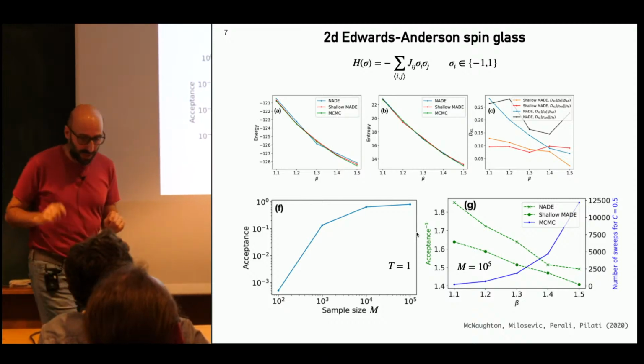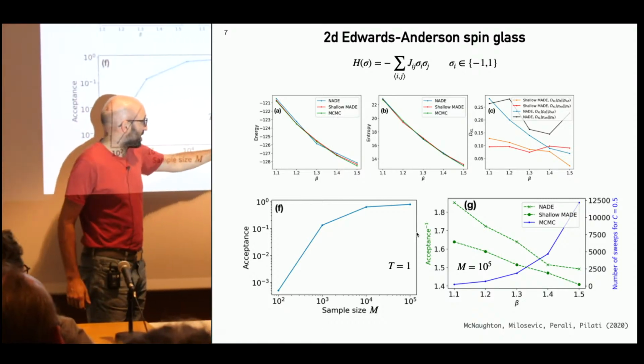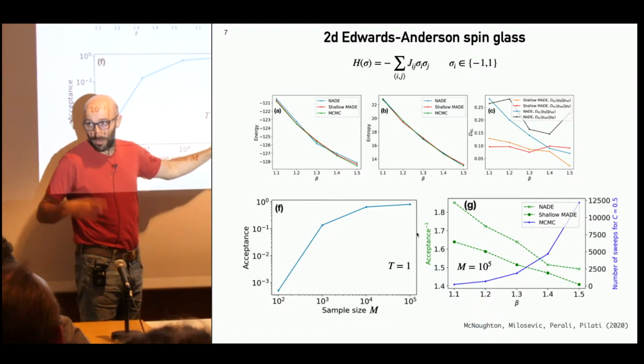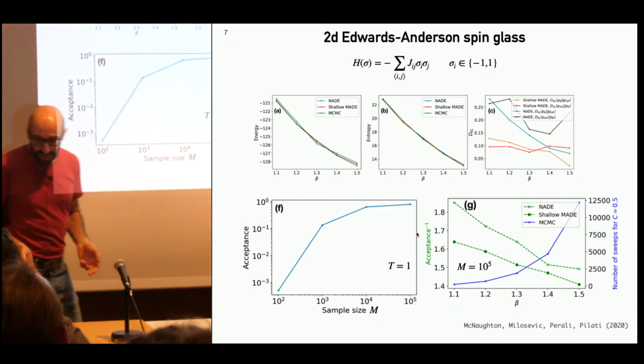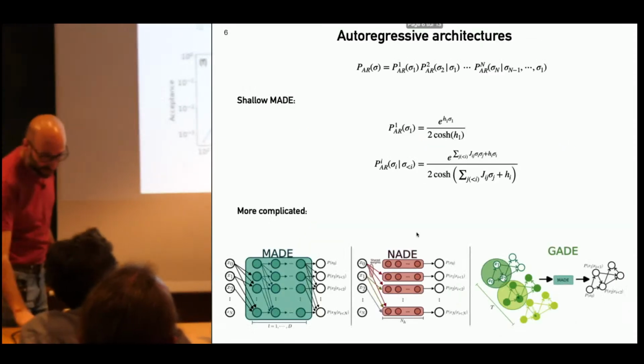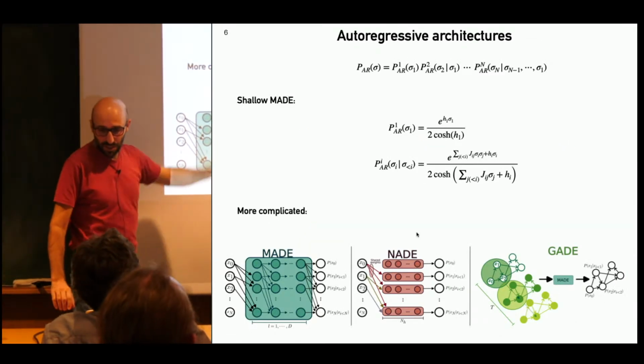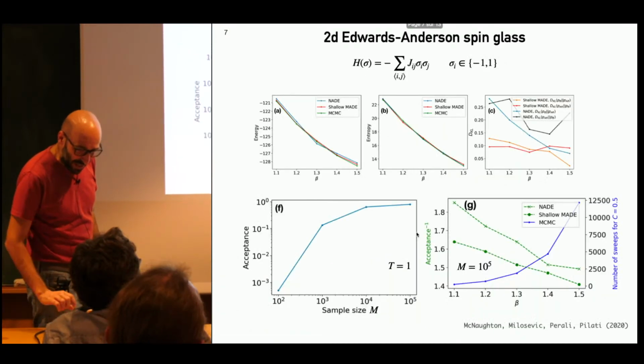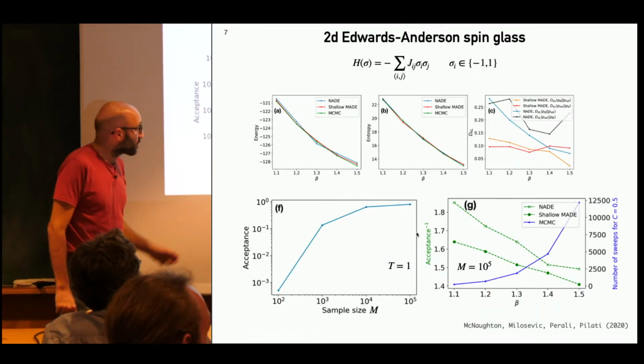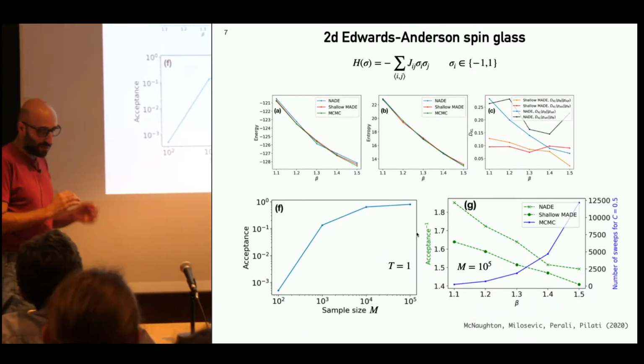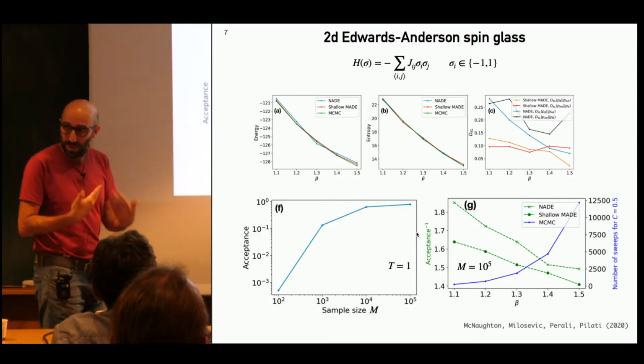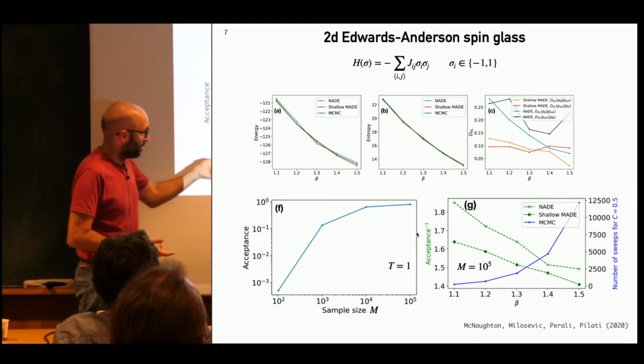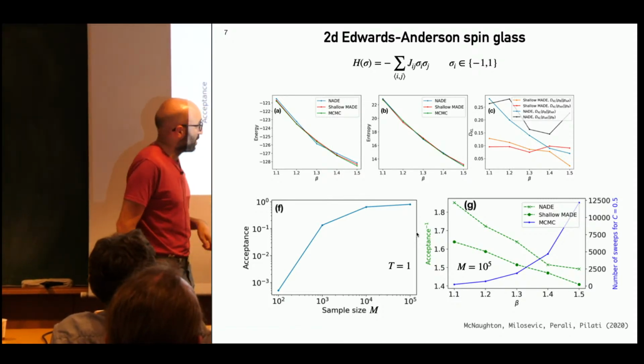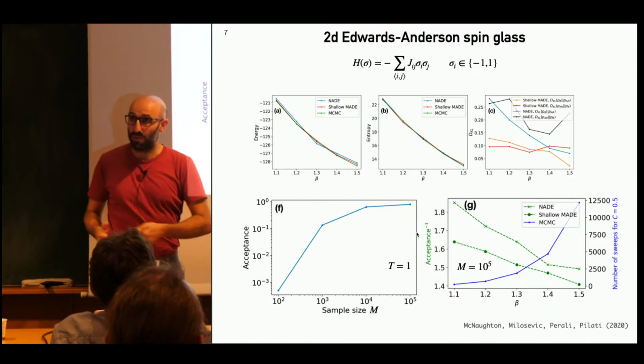And so what we did is we start by generating a sample at temperature 1, where the local Monte Carlo is very fast. We train a model. In particular, we took this one, the shallow one. We train this model, and then we lower the temperature a little bit. We run the global Monte Carlo using the model we just learned. We generate a new sample, and we keep going.